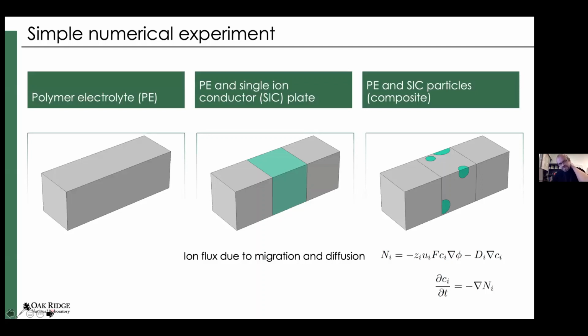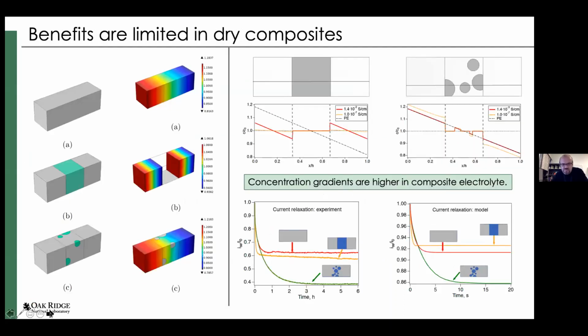So this is a simple numerical experiment where you have a purely polymer electrolyte domain, then polymer electrolyte and the single ion conductor, in this case, LATP membrane placed right in the middle, and the polymer electrolyte and the composite in the middle. And just to see what placement of the single ion conductor would do to the overall gradients of the lithium cation concentration in the system. The hope is that it will reduce the gradients and increase the transport number. But if you do, like I said, the simple numerical experiment, you can see that the effect is actually opposite.